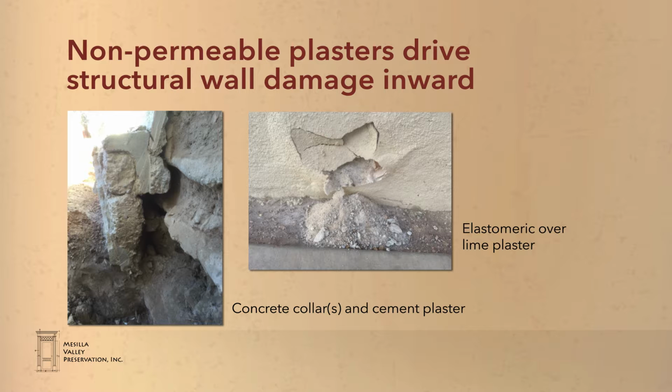The photo on the right shows an example where positive remediation was done initially, and then, unfortunately, reversed. This salt-laden wall was appropriately treated with lime plaster several years ago. The lime plaster has been doing its job and migrating remaining salts to the surface. Unfortunately, the contractor responded to the reappearance of the salts by coating the building in an elastomeric coating. Of course, the salt damage continued behind the elastomeric coating, causing the rubberized surface to bulge and blister.